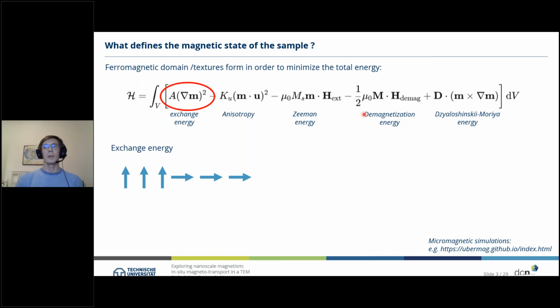If we assume a magnetic state like this one here at the bottom, we have 6 magnetic moments, and they are just aligned like that in the starting configuration. If we simply have the exchange energy and want to minimize it, we will end up with a magnetic configuration which looks like that. All the magnetic moments are aligned parallel to each other and slightly inclined, depending on the starting configuration.